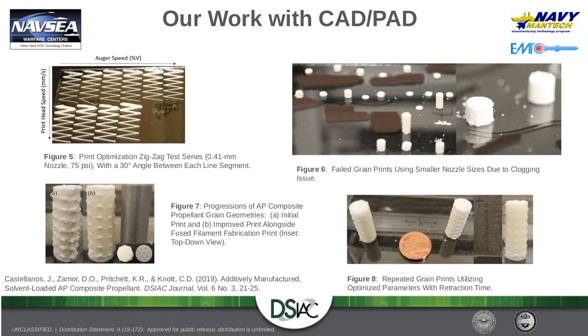So can I. With regards to the substrate, obviously the cleaner you have your environment, the better it is. For this material, the best results we got were with a very clean substrate. With regards to the material, I can talk a little bit about it, but then I'll hand it over to Jorge to elaborate more. We found there was a lot learned in handling the material and preparing it, and cleanliness definitely came into play as a big factor.